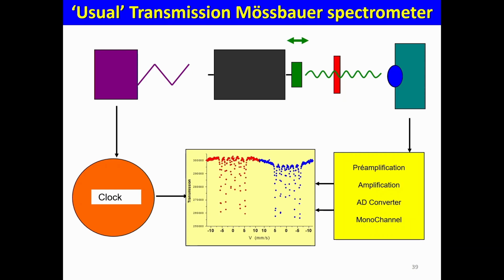But I want to say that a Mossbauer spectrometer is composed of some generator of movement, because you have your source. If your source is fixed, you have a single energy. How to have a scanning of energy? By Doppler effect. You know what is Doppler effect? Okay, so if you have Doppler effect, that means you will move the source and you will provoke a scanning of energy. So you have your sample, your source, your detector, you have a lot of electronics, and you will get, finally, on the scope, this kind of image.